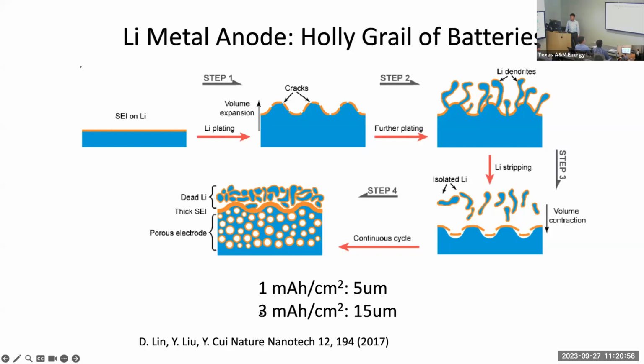For lithium plating in a practical cell, we oftentimes need 3 milliamp hour per square centimeter, or 5 milliamp hour. That's 15 microns of lithium for one layer of the electrode. So when you do plating, you plate 15 microns. When you do stripping, you strip away 15 microns. Your battery consists of multiple layers of electrodes. This battery cell is going crazy.